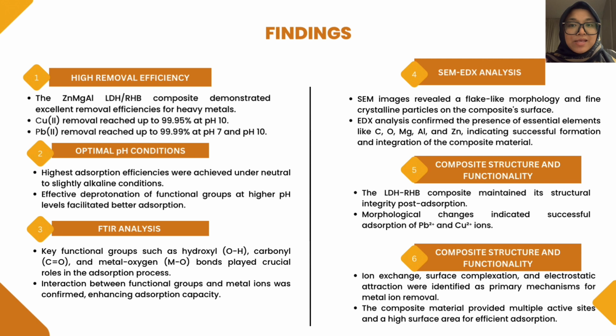Next, I found that the highest adsorption efficiencies were achieved under neutral to slightly alkaline conditions. The effective deprotonation of functional groups at higher pH levels facilitated better adsorption. This means that the composite works best in environments with pH levels around 7 to 10. The FTIR analysis provides significant insight into the chemical interactions involved in the adsorption process. I identified the key functional groups such as hydroxyl, carbonyl, and metal-oxygen bonds. These groups play crucial roles in the adsorption process. The interaction between these functional groups and the metal ions was confirmed, which enhanced the composite adsorption capacity.